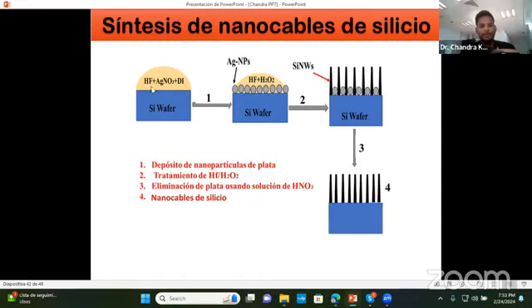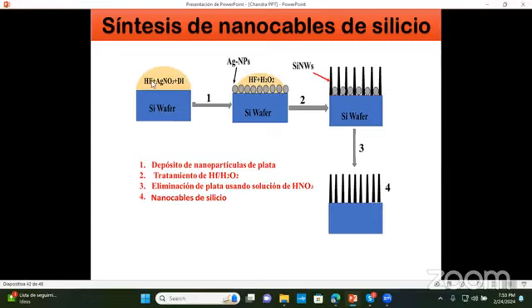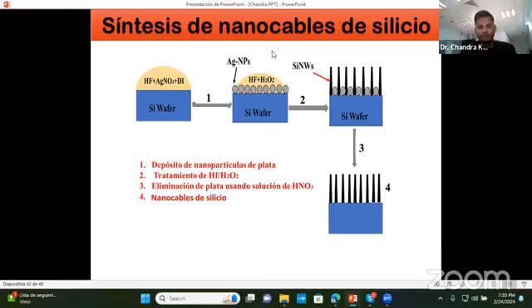We have to deposit a silver layer through either a physical technique or a chemical technique. Once the silver layer is deposited, we have to dip that in a solution of HF and H2O2. Okay. After that, the etching mechanism takes place.